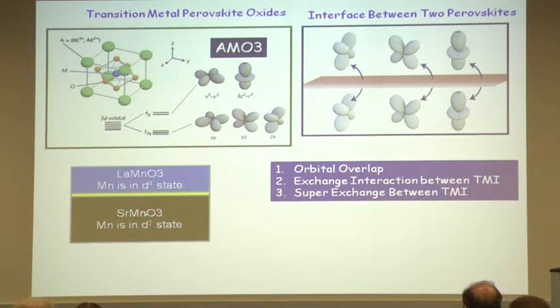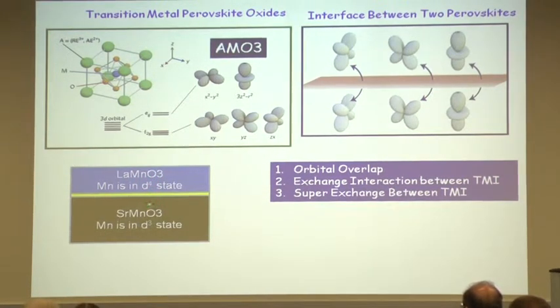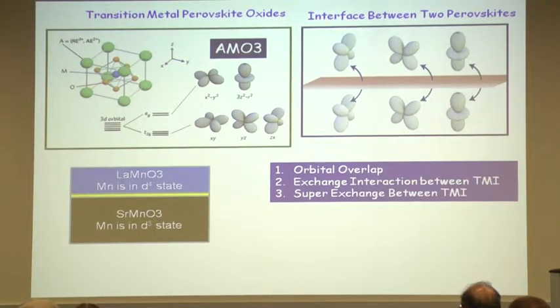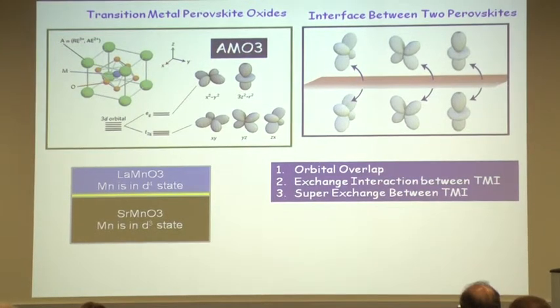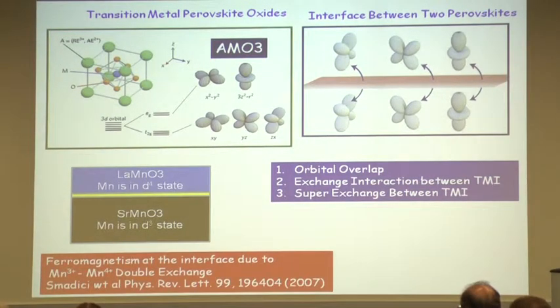If you take strontium manganese oxide, here the manganese in D3 state configuration, and lanthanum manganese oxide, here it is D4. And at the interface, one can have an interaction between Mn3 and Mn4 through an oxygen ion. And that's what gives you the so-called double exchange, a special case of super exchange. And because of that double exchange, the interface can be ferromagnetic. Also, it can be metallic. And beautiful work in this area has been done here at Argonne.